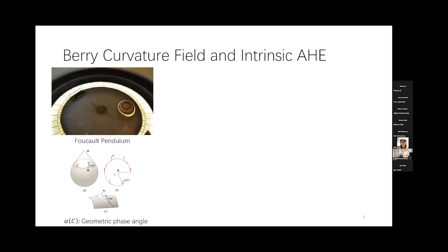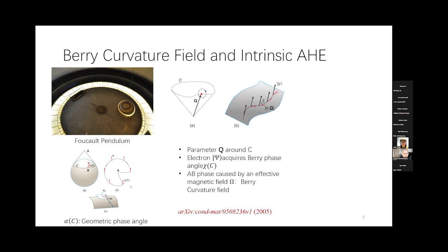For the intrinsic anomalous Hall effect, we understand it as a Berry curvature field effect, which is similar to a geometric phase. So this is a pendulum on Earth. After 24 hours, you notice the direction of the pendulum will rotate by an angle, which we call the geometric phase angle. That's the reason we can use that to describe the topological property of a sphere when it's rotated. For electrons, you will see a similar behavior. If you have a parameter space Q, which has a closed circle around C, the electron wave function will acquire an additional Berry phase angle. And we assume there's an effective magnetic field in K space, which will produce this Berry phase angle.